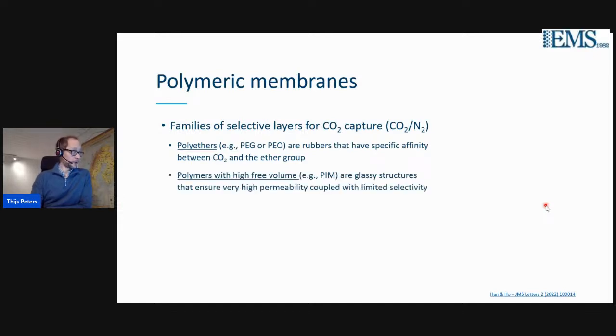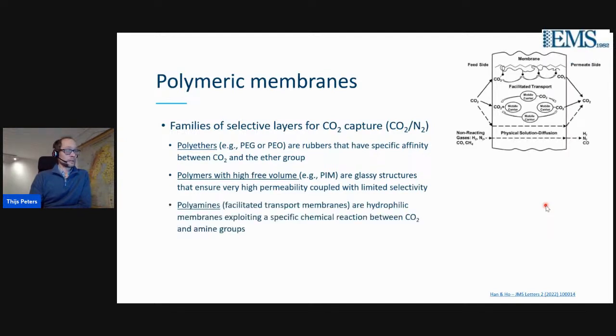Another polymeric family is the polymers with high free volume, for example PIMs. Those are glassy structures that ensure a very high permeability over CO2, but unfortunately coupled with sometimes a quite limited selectivity. Another polymer family are the polyamines, which normally is a polymer material relevant for facilitated transport membranes. These are hydrophilic membranes that exploit the specific chemical reaction between CO2 and the amine groups that constitute the membrane, which means that you need water vapor. You need to humidify the membrane up to very high relative humidities for the CO2 to permeate through the membrane.